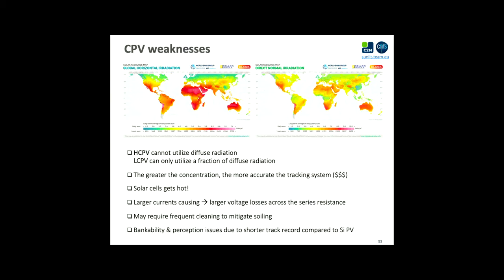There are some drawbacks or problems or things to take care of. First of all, you need direct light, so diffuse light from clouds won't work because your optical element won't focus properly the light. And so the distribution of direct light is lower than the conventional global, direct plus indirect light, and you normally have these in deserts or whenever you have a clean atmosphere without clouds. So you can't use diffuse light. This is a problem. Then the other problem is that you have to track the sun, because you are concentrating the light, and your optical element will work only if you're directly looking at the sun. So the higher the concentration, the more accurate should be the tracking system, and the higher will be the price of your tracking system.